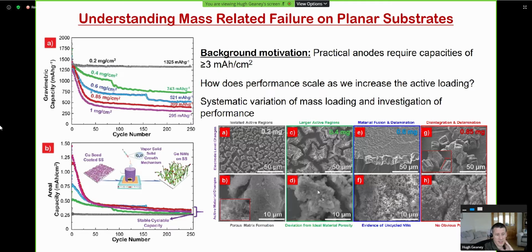And what we started to see was this deviation from the ideal material porosity. So we started to see almost chunks of active material that had come off and become inactive or had stopped cycling. As we went to 0.6, we started to find these larger regions where the material had fused together. And we also had evidence of uncycled nanowires here. And then as we went to the higher loadings again, you could see that we had a disintegration and delamination as well. So the material was no longer properly connected to the current collector and had broken away.